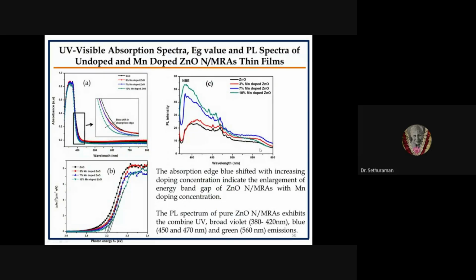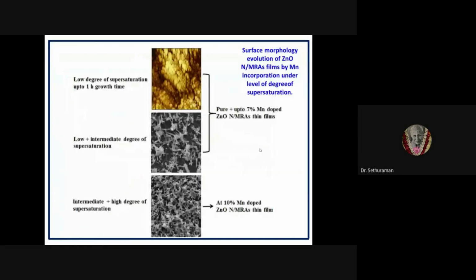We also observed the UV-visible absorption for the seeded, pure undoped as well as the doped zinc oxide nanorod assembly. From that, we found a blue shift with increasing doping concentration, which simply indicates the enlargement of the energy band gap of the zinc oxide nano micro rod assembly with Mn doping concentration. From the PL spectrum, pure zinc oxide nanorods exhibit a combined UV and broad violet, blue and green emissions.